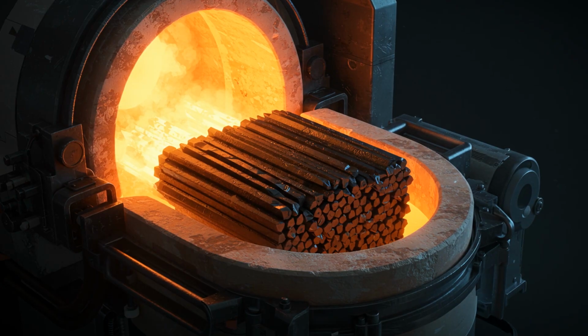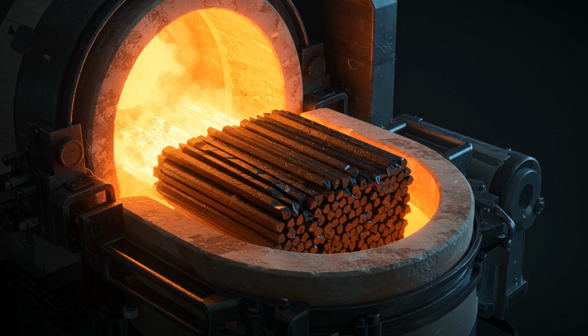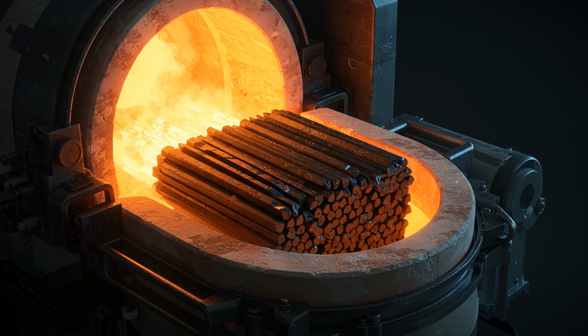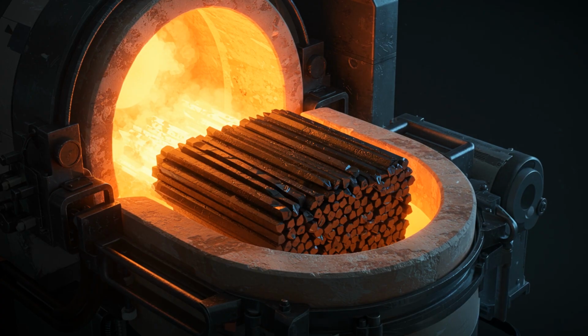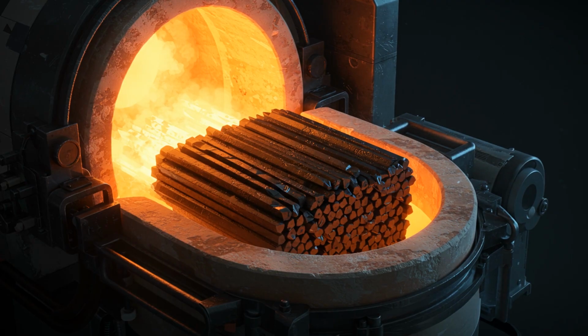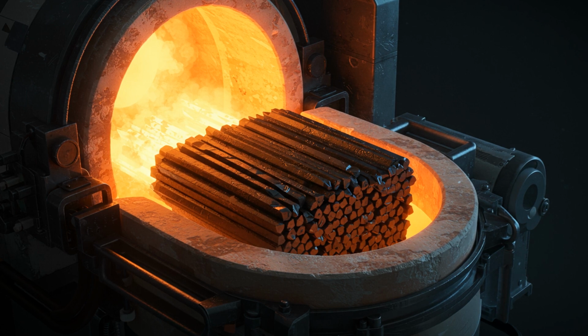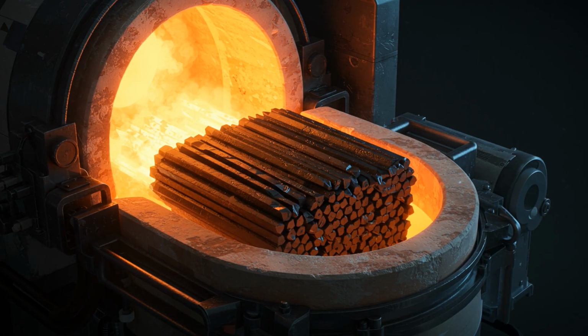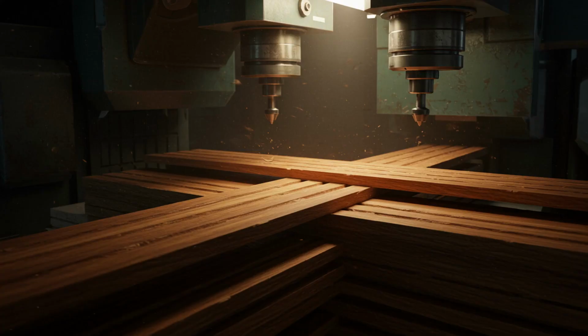The timing must be perfect. If the leads are fired for too long, they become brittle. Too short, and they remain soft and useless. After several hours in the white-hot heat, the leads are slowly cooled. They emerge as hard, metallic-looking rods. But there is one final chemical treatment required. To make the pencil write smoothly, the porous ceramic structure must be filled. The leads are submerged in a bath of hot wax and fats, which soak into the microscopic pores of the lead, acting as a lubricant that allows the pencil to glide across the paper with zero resistance. While the core is being forged, the armor is being prepared.